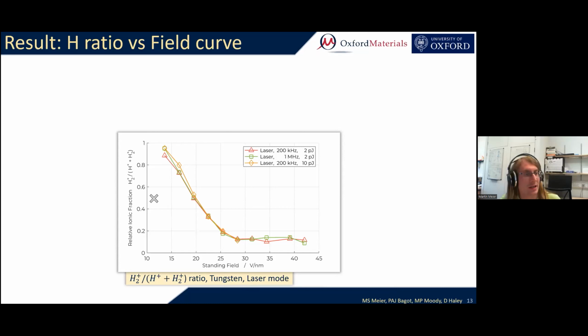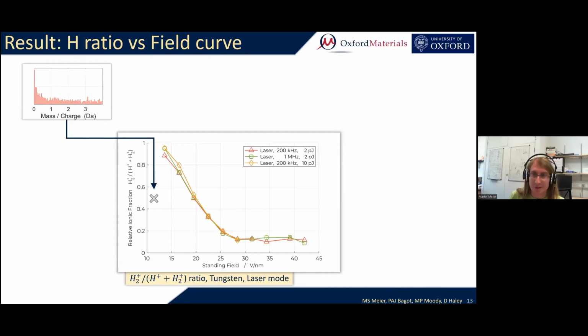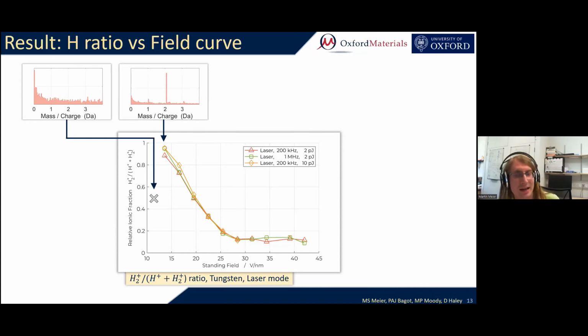Now, when we go through it in a bit more detail, the first data point that you see in here is a gray X, and that's the symbol that we use for an empty spectrum. So if the electric field is too low, there's just nothing evaporating at all. But then if we just go a bit higher and evaporation starts, we see a spectrum, and that's, as expected, dominated by the H2+ peak.